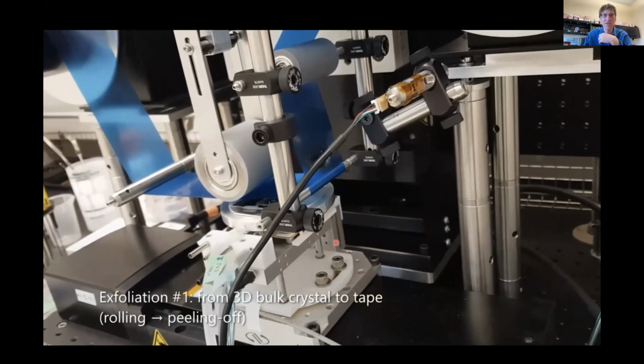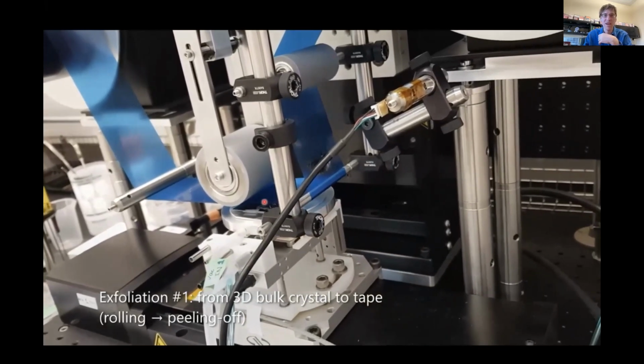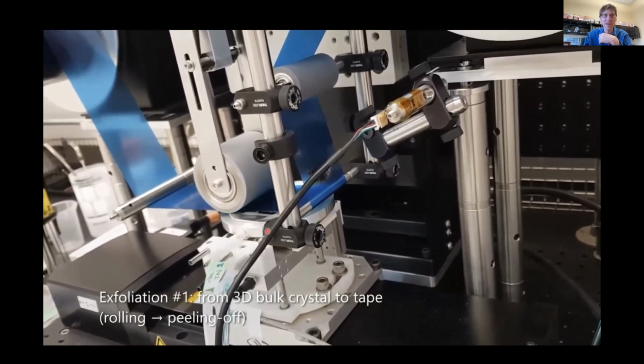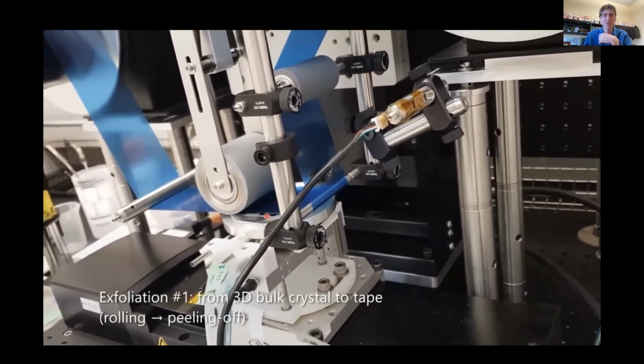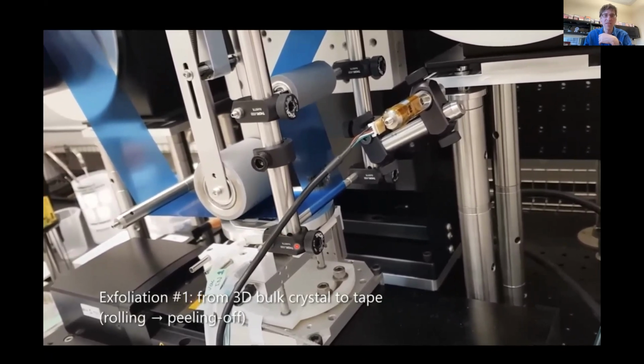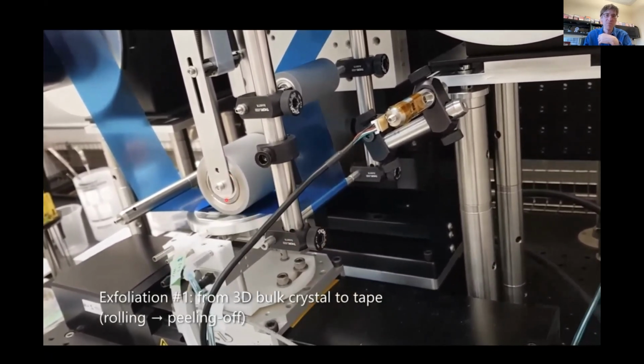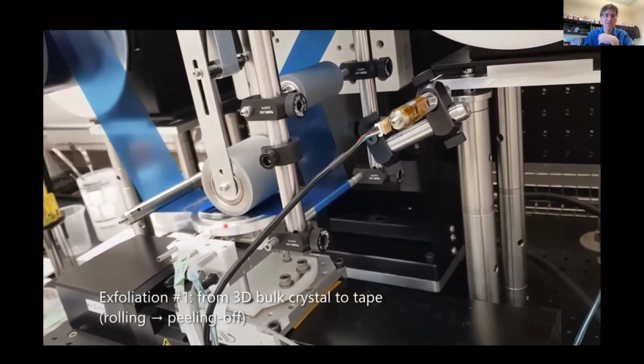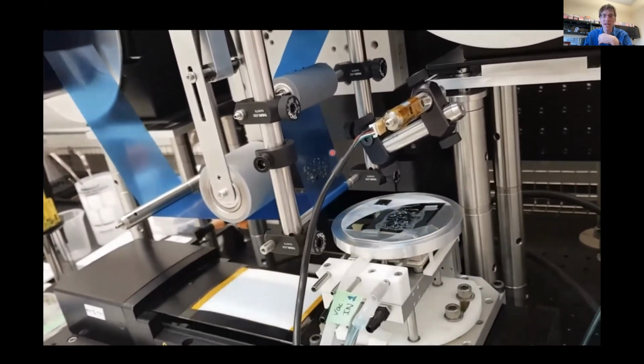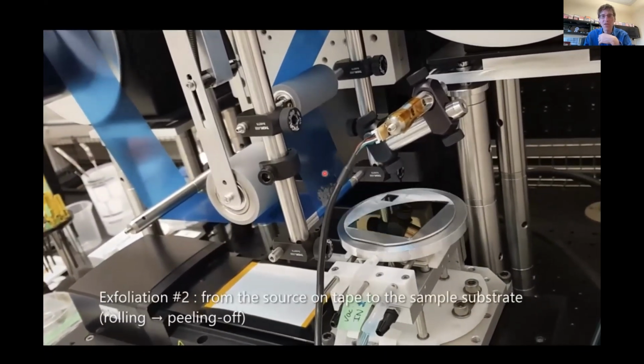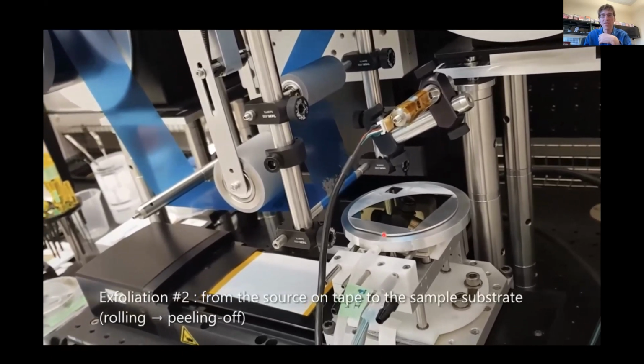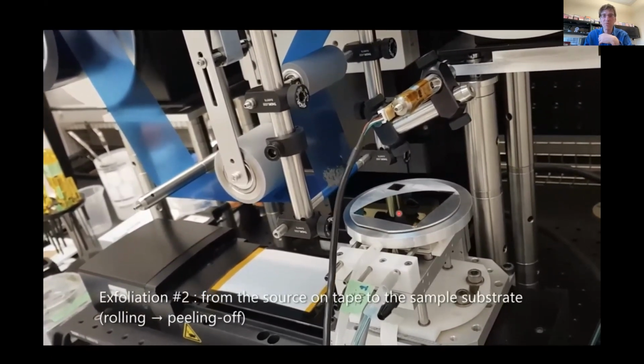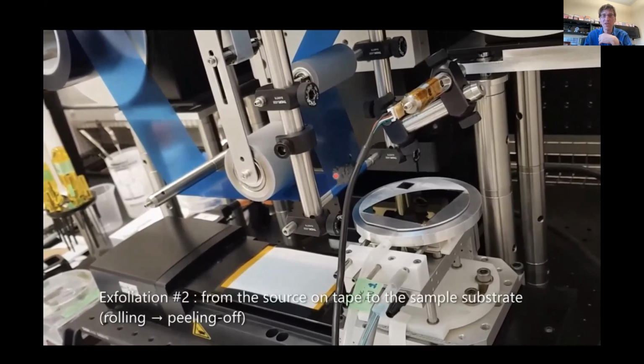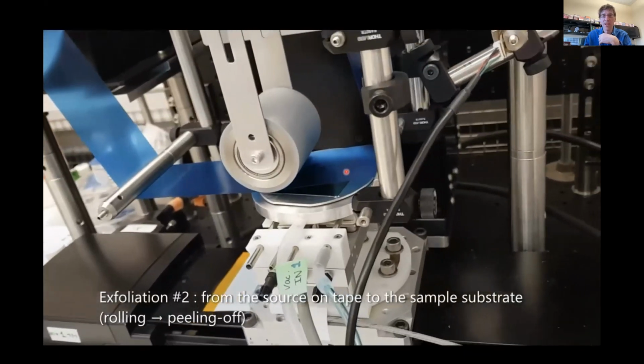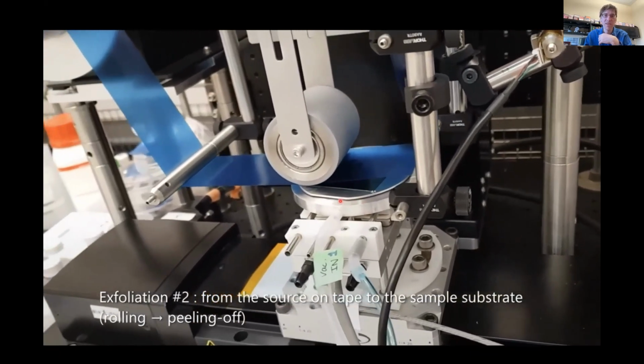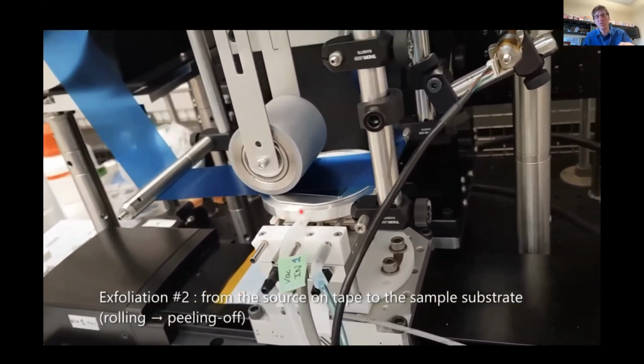And again, let's zoom in on this movie here. You can see in this movie, there's some crystal material on there, and we approach it. We press down with the roller, and then we move side to side to apply this pressure to the flakes. And then we move here, and you can see a bunch of crystals have been transferred to the tape from the substrate. And then we bring in this fresh substrate that has nothing on it, but you can see the crystals are on our tape. We bring it in, we press down, and we do another rolling operation.